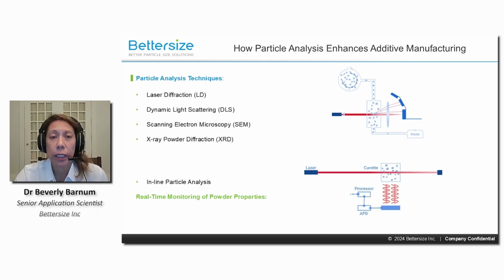What are the particle analysis techniques? Common ones are laser diffraction, dynamic light scattering, SEM, X-ray diffraction. Diving into these really quickly, laser diffraction is a widely used method for measuring particle size distribution and is particularly useful where narrow PSD is critical. This typically measures diffraction in the particle size range from 40 nanometers to 3,500 microns. The advantage is that it's fast, non-destructive, and suitable for a wide range of particle sizes.